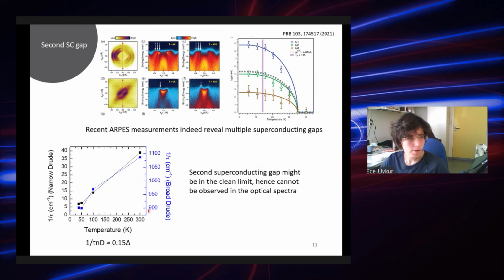But we didn't observe it, and when we look carefully at the scattering rate of the narrow Drude, which I plot here for both, the black curve belongs to the narrow Drude component, it's actually quite small compared to the gap value, which means that this superconducting gap, the larger one, might be in the clean limit, and it would not then be visible in the optical spectra. So if your Drude component is quite sharp, this puts these carriers in the clean limit, which then disappears from the optical spectra as a gap.